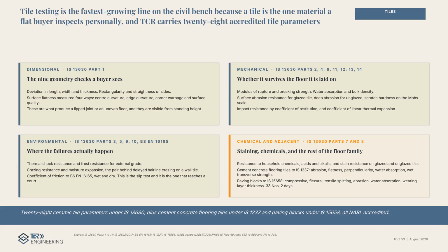TCR carries 28 accredited ceramic tile parameters under IS 13630. 9 of them are geometry: length, width, thickness, rectangularity, straightness, and 4 separate flatness measurements. The rest covers strength, abrasion, water absorption, thermal shock, crazing, frost, and the coefficient of friction, wet and dry, which is the slip test that reaches a court. Sample: 6 to 24 tiles, depending on size, 20 days.